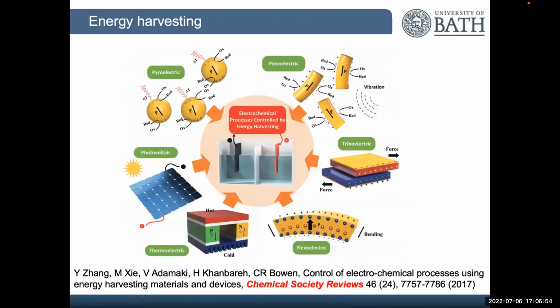So in a lot of cases in energy harvesting, we're doing that to develop low-scale power and to store our power for wireless networks, milliwatts, for example. But certainly people are now moving, rather than having a storage capacitor, to use that harvested energy to affect an electrochemical process. So there's certainly work looking, as Haito has said, at pyroelectric materials and piezoelectric materials, where that charge and that voltage is used to affect electrochemical reactions, water splitting, dye degradation, for example. And obviously people are doing that with photovoltaics. You can do that at scale, obviously, for hydrogen generation, and with thermoelectrics, but because of the ferroelectric nature, I'll focus the last bit of the talk on piezo and pyroelectric.